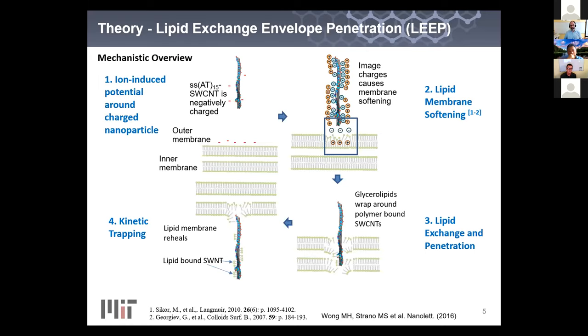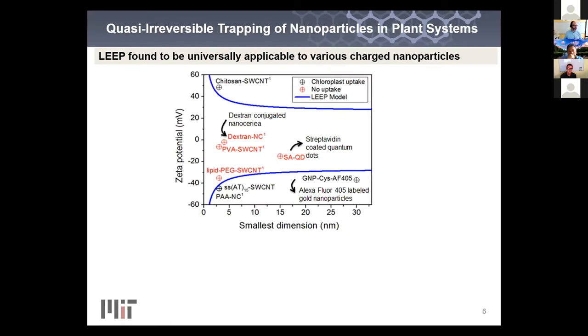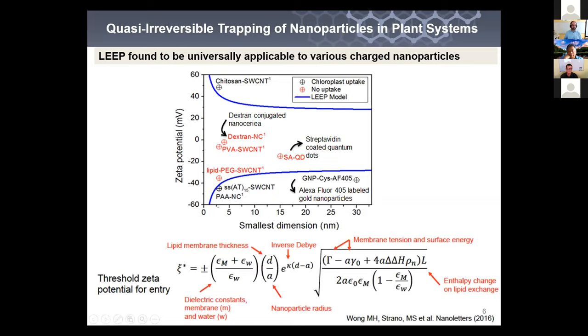If you put equations to all those steps, you work it out, you come up with this theory, which so far describes a broad range of plants and almost any nanoparticle. We're still looking for exceptions to it. The zeta potential versus the size of the particle, the equation, which I'll show, but I don't want to overwhelm, has positive and negative solutions. So it basically predicts that if a particle has sufficient charge for its size, it can traverse any biological membrane using this particular mechanism, which we call LEEP, lipid exchange envelope penetration.